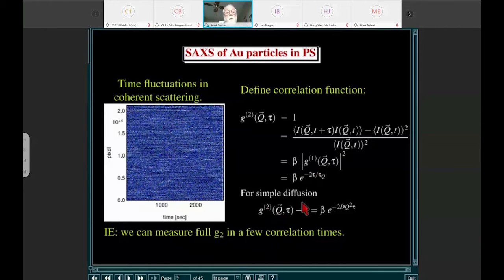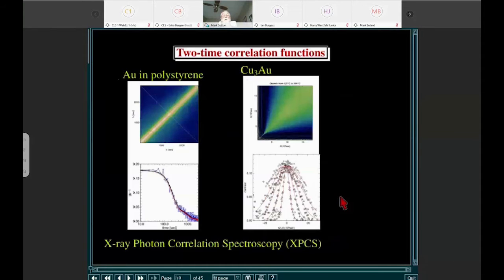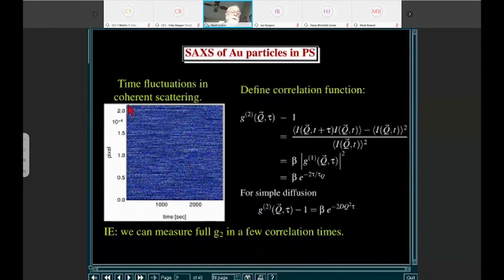So for simple-minded linear diffusion, the intensity-intensity correlation function, normalized by the average, exponentially decays with the diffusion constant. By measuring the time constant as a function of Q, we get the diffusion constant. But for this non-equilibrium stuff, I'd like to point out one extra thing. We have lots of speckles. For isotropic scattering, every speckle that has the same magnitude of Q has the same equation of motion. That's what isotropic means.